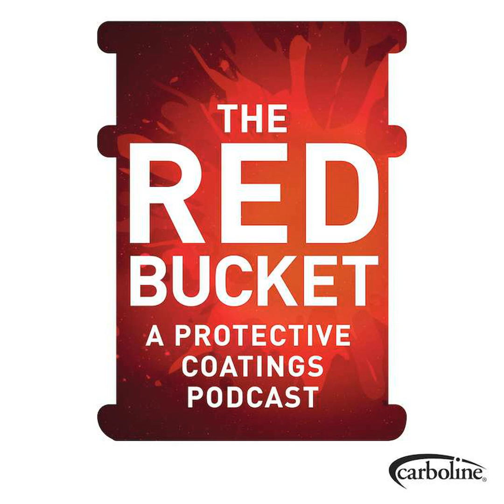In the case of putting zinc onto metal using a paint vehicle, what you end up with is these zinc particles, in the case of an inorganic zinc, in a silicate matrix. And I keep saying rock-like because it really is. It's sand, rock, whatever, silicates. These silicates over time will react with moisture and continue to cure over time.